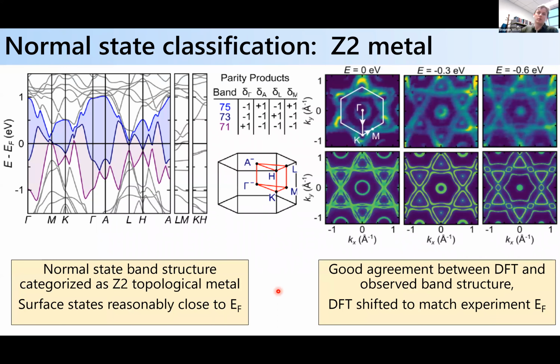But what you can do is look at the normal state electronic structure of the system, and this is some work that Sam Teicher did. You can just try and do a topological classification of the normal state metal. If you do so, then you can identify a continuous direct gap across the system, and by looking at the parity of all the bands at the time reversal invariant momenta, you can identify the system as a Z2 topological metal, which means that it should have topologically protected surface states. And Sam was able to do this classification and identify surface states reasonably close to the Fermi level at the endpoints, okay? And I'll show that on the next slide.